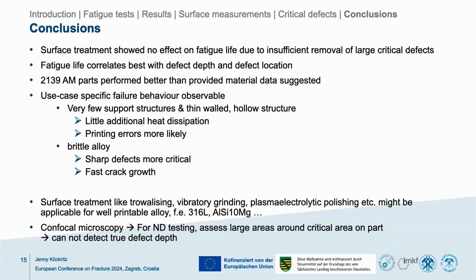In conclusion, we could see that in our use case, the surface treatment didn't show any effect on the fatigue life. The reason for that was that the surface treatment that was selected, this industry standard surface treatment, wasn't able to remove all the deep crevices, which is where the fatigue cracks initiated. The fatigue life correlated best with defect depth and defect position. And I have to add, even though I showed all these huge defects, that the parts that we produced and that we tested performed much better than the material values of, well, actually fatigue tests that were done with this alloy by the producer who provided us with these parts. So still the parts outperformed the expectations that we had.